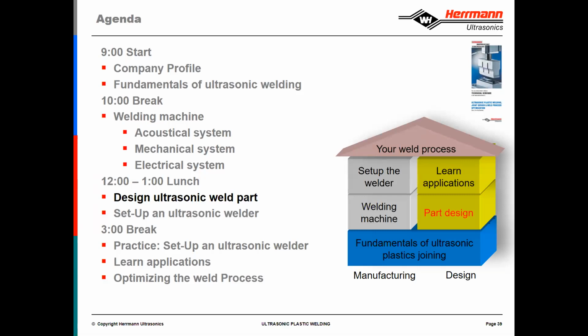Sure. So the variability of the welding process is directly tied to the consistency of the molded parts. Ideally, if you have a single cavity mold for part A and a single cavity mold for part B, then the consistency should be 100%. It should be the same from weld to weld. If you have a multi-cavity mold, or if there is variability in the molding process, that will typically be seen within the weld process. And we do have tools at our discretion that we can choose the right process parameter. It might be energy, it might be distance, but oftentimes we choose distance as our primary weld parameter, and that's driven by the height of the energy director. So as long as the height of the energy director stays the same, the welder will adjust the amount of power and the amount of time that goes into the weld to accommodate those variables that you might see in molding.